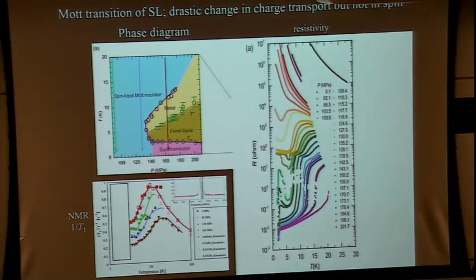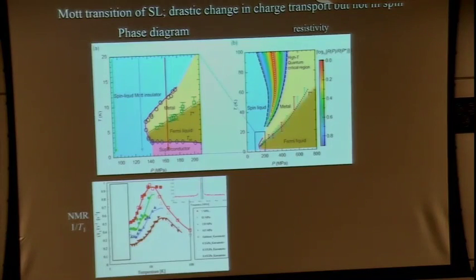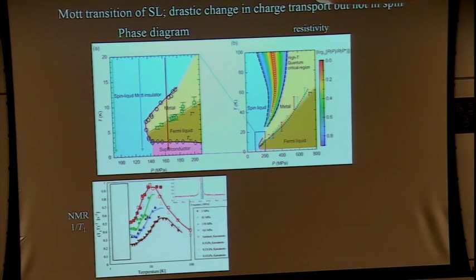Okay, this is the low temperature behavior, and additionally, interesting behaviors occur at high temperatures. This is the phase diagram in these regions. If you look at the high temperature regions of this phase diagram, extended up to 100 kelvins, there is a very interesting crossover region, which is indicated by a range of colors. And this is the quantum critical behavior. It's shown in these regions. So I'd like to show some results concerning this finding.